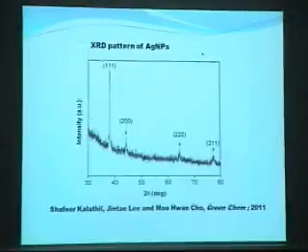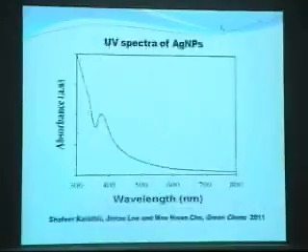So this XRD pattern is very typical for silver nanoparticles, showing some different planes. If you look at this, there are no peaks other than silver peaks, which shows the high purity of the nanoparticles. If something were happening in the nanoparticle, like silver oxide forming, there would correspondingly be some peak here. But there are no other peaks, only the silver peaks, showing the high purity of the synthesized nanoparticles.